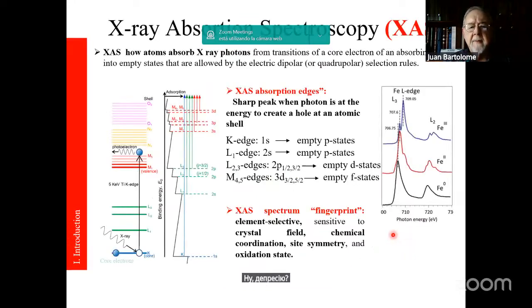Now, the basic experiment on which all this technique hangs is X-ray absorption spectroscopy. XAS, in short, is the way atoms absorb photons, and it lets transitions happen from the core-created hole to the available empty states at higher energy that may be allowed by electric dipolar or quadrupolar selection rules. Now, when the light shone coincides with the energy of one of the shells in the atom, we get a strong, sharp peak, which we name the absorption edge.